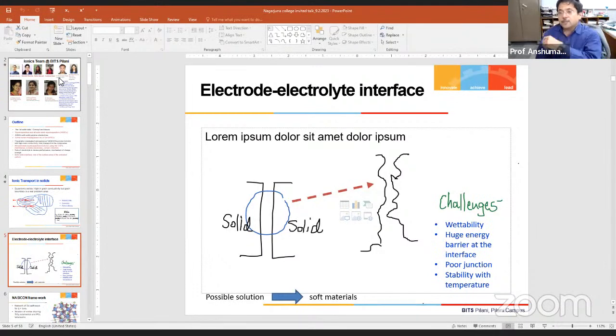Then there is another issue, the thermal expansion. Thermal expansion coefficient: if you want to go to high temperature, then different materials will have different thermal expansion coefficients, and one of the materials will expand more, another one will expand less, and that also is a reason for the poor electrode-electrolyte interface. Because of various reasons, the energy inside the solid electrolyte may increase, and those things may cause a poor interface again. So interface is one of the important things on which all the solid-state ionics people, the people who want to use solid electrolytes for batteries, are actually working.